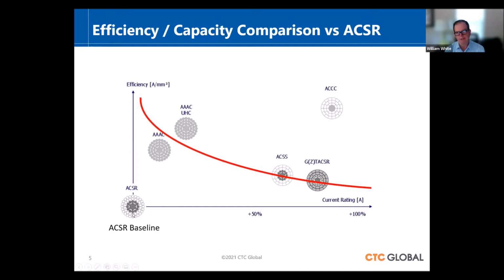This is the industry standard, and this looks at the capacity of the line on the horizontal axis and the efficiency of the line on the vertical axis. And you can see that some of the products that have been introduced over the years have achieved better performance on one or both of these metrics, but really ACCC stands out as being sort of an outlier. And again, that has to do with the material that's being used in the core of the wire.